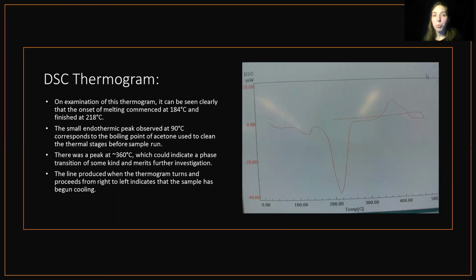Melting thermograms were obtained for both samples. Both of the thermograms agreed. The thermograms show that the samples began melting at 184 degrees Celsius and finished at 218 degrees Celsius. There is a small endothermic peak observed at approximately 90 degrees Celsius, as shown in the figure on the slide, but this corresponds to the boiling point of acetone, which was used to clean the thermal stages before the samples